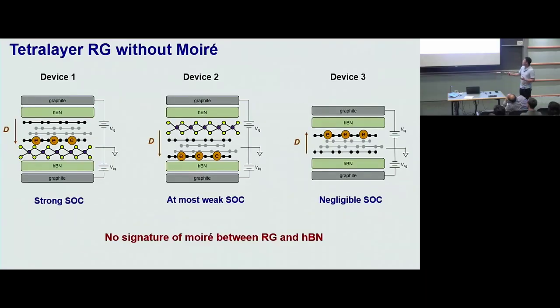Okay, this time, let's focus on tetralayer graphene. We have three devices. Device number one has a WSe2 layer, and it has good contact when the electrons are pushed towards WSe2. So there is strong spin-orbit coupling. Device two has good contact when the electrons are pushed away from the WSe2. So this may have some weak spin-orbit coupling, but maybe non-zero. Okay? Device 3 has no TMD. Device 3 is just a bare tetralayer rhombohedral graphene. And we see superconductivity in all three devices. And guess what? The Tc is highest in this one, intermediate in this one, and lowest in this one.